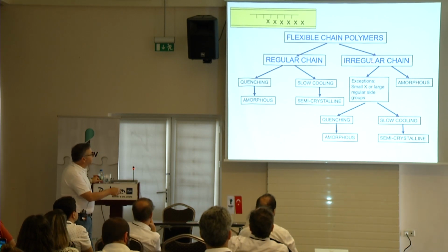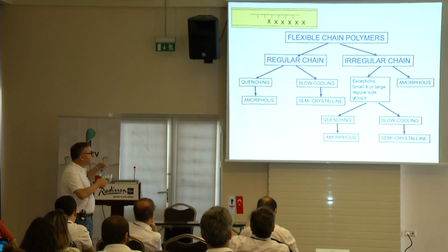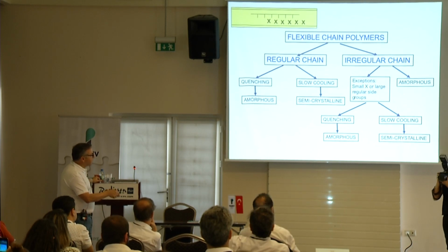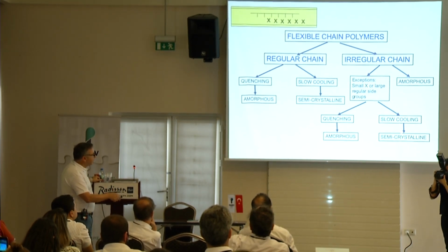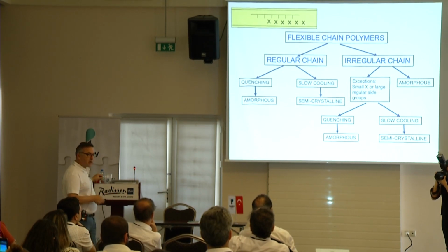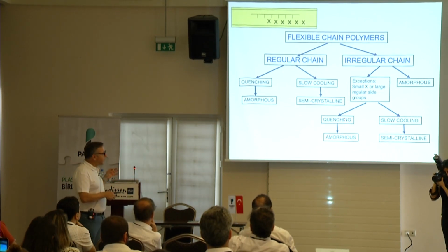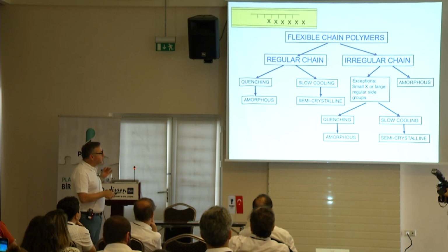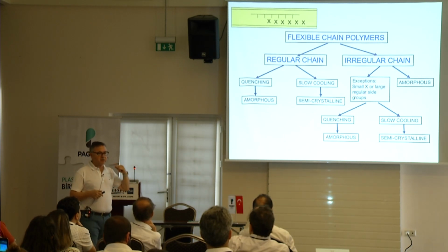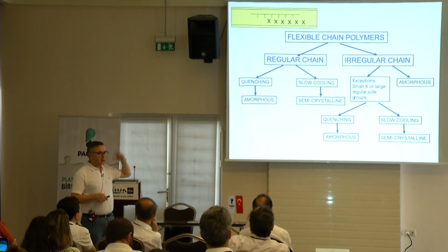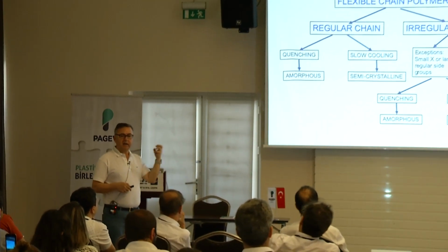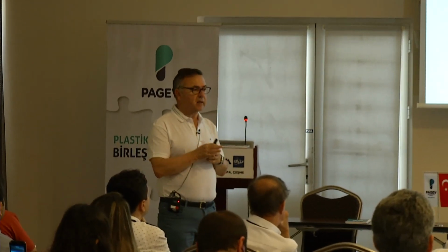But sometimes, even though it may be atactic and non-regular, if you have a small X, they actually can crystallize by slow cooling, or you can quench it into an amorphous state. Remember, this is all a kinetic process. If you cool fast enough, these materials, which usually have a glass transition temperature above room temperature, you can quench into a glassy state, and in that state they can be metastable. They can just sit there until something happens to them. You heat it up, and it will have enough energy to crystallize, or just simply a slow aging process.